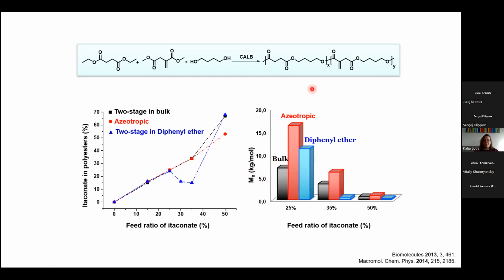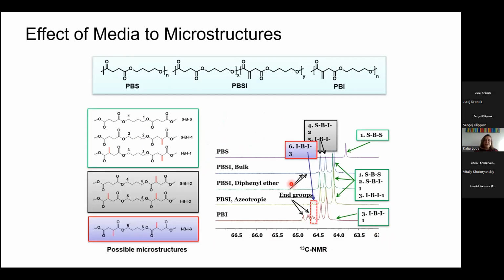And here again, what I already showed you, we can play with the way we do the polymerization. If you do 2-stage in bulk, it's different than 1-stage in bulk, which is not even in the slide. But if you do an azeotropic polycondensation, you get higher molecular weights. And we can also tune, which is difficult with melt polycondensation, different feed ratios of itaconate or itaconic acid, so you can really steer how much itaconic acid is later in the polymer. And also here, this was the first time we actually studied all the different ways to do the enzymatic polycondensation, with what microstructures and what end groups we get. And it's really extremely interesting to look into that.